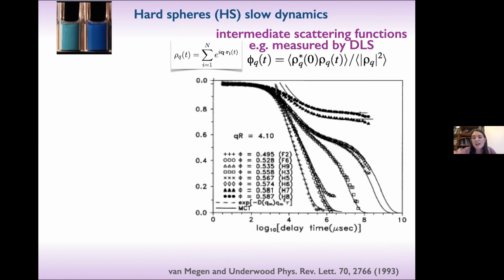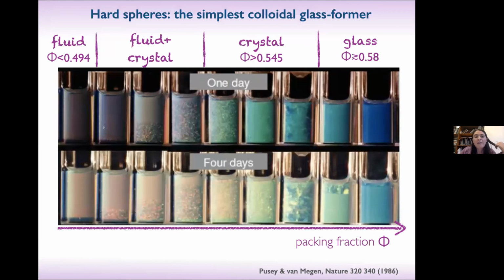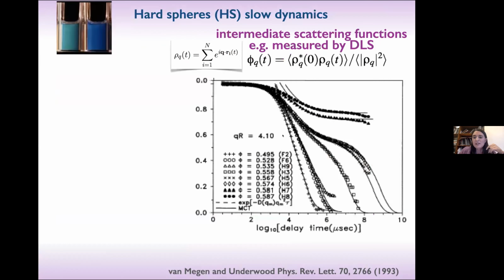Of course, later there have been other measurements, for example by Luca Cipelletti's group, that have largely extended this time window, but for the purpose of this talk, it is sufficient to focus on the old data of Bill van Megen. One important point I want to underline is that, as you saw in the previous slide, here we have the fluid-crystal transition. But in the experiments here, we see no sign of crystallization because colloidal hard spheres are intrinsically polydisperse, and polydispersity suppresses the tendency to crystallize.